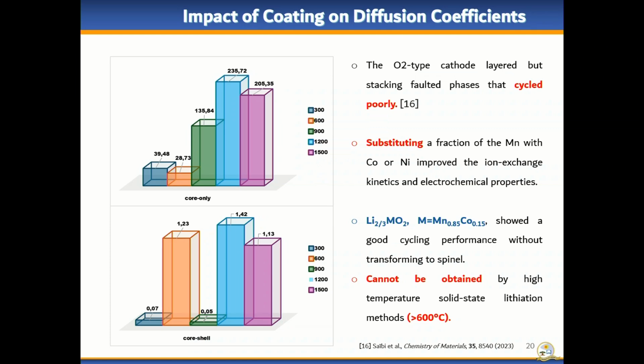So we went back and tried to find out from literature what could be happening. We found that the stacking fault of our O2 type structure is not always a good thing, especially with the manganese alone. In some studies, they actually did transition metal doping to try and improve the cycling performance of the O2 type structure. Another thing, in terms of temperature: because this is a metastable structure, it cannot be obtained at temperatures greater than 600. So maybe this can explain what is happening there at 900. But this is some preliminary PhD work, so we'll still look into what is really happening there.